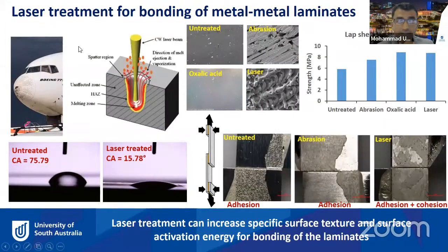We also have been recently doing the laser treatment on metal laminates, metal and metal laminates, to increase the bonding strength between the two sheets. And this is just one example of that. So we have compared the laser treatment as well as other commonly used treatments like abrasion and oxalic acid treatment. So this is the laser treated surface of the metal sheet.